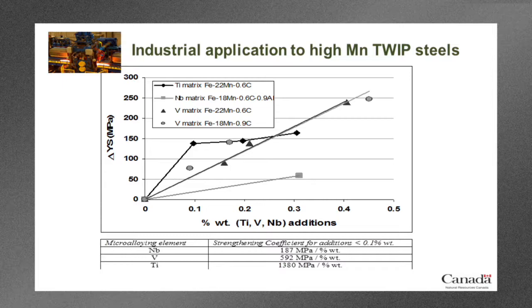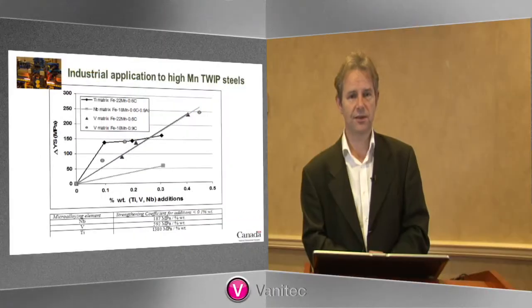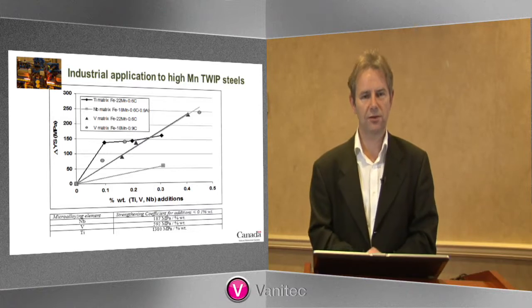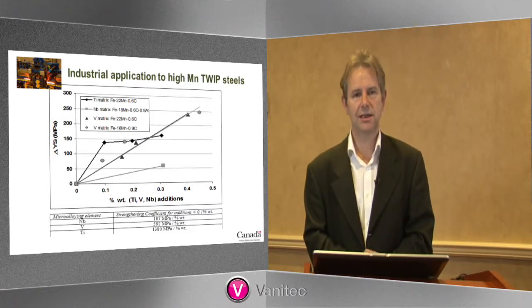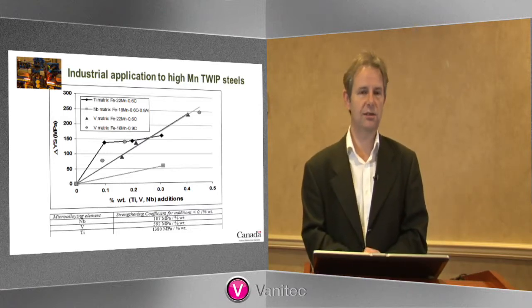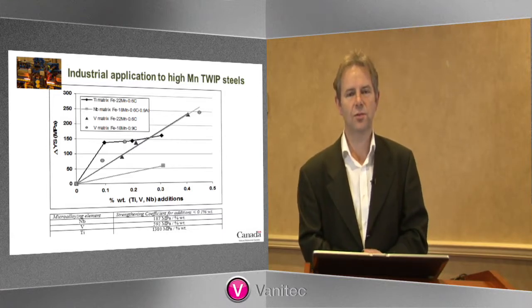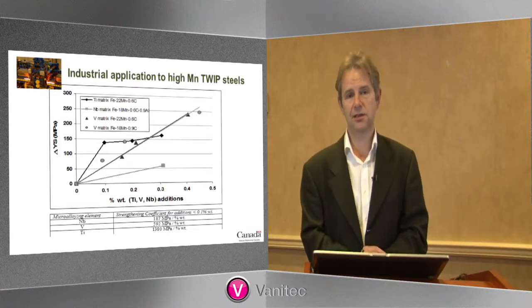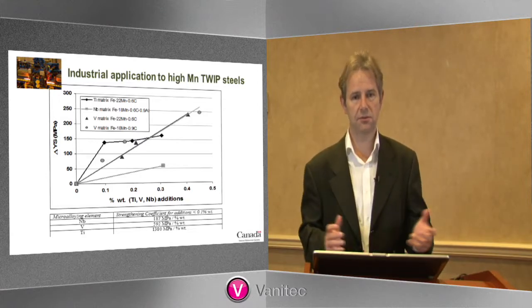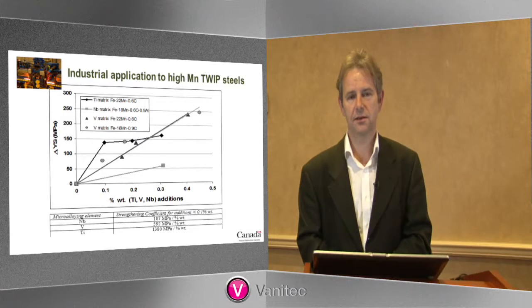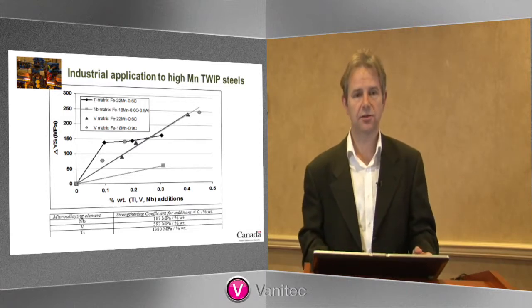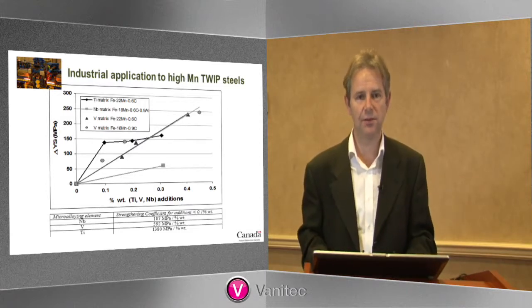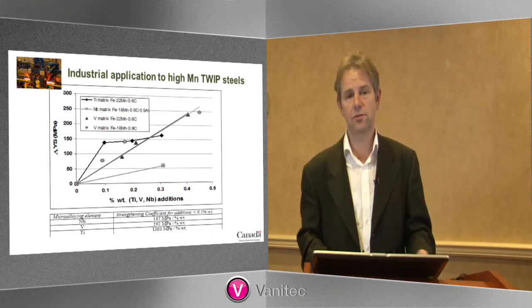And the triangular points are vanadium data from two different types of steels, one where we had 22 manganese, and the other one where we had 18 manganese. You can see they more or less superimpose each other. The strengthening is very effective, and it doesn't saturate, unlike the titanium. So we would say that vanadium is the best strengthening precipitate for these types of high manganese steels, and it could also be applied to medium manganese steels and newer steels, about 10% manganese.